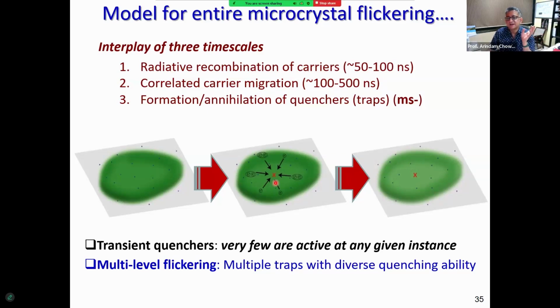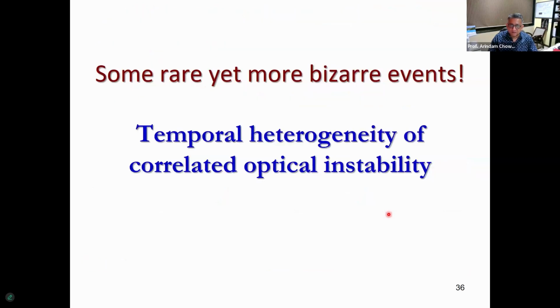So imagine that you have no traps, the crystal emits. If you have one single trap, then the carriers would get drawn by correlated motion towards the trap, and there's going to be some sort of quenching. When the quencher deactivates or disappears, the light emission of this entire crystal restarts. So this can also explain the multi-level flickering instead of a single level. We believe that multiple traps are formed, not too many, nor too few. So only a few of them are active at any given instance, which gives this kind of multi-level fluctuation on top of a background intensity.